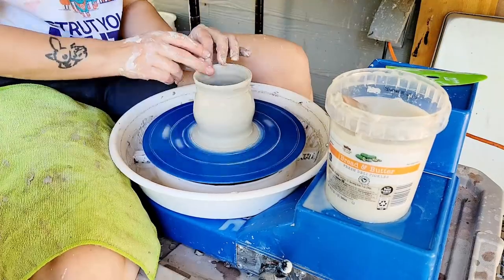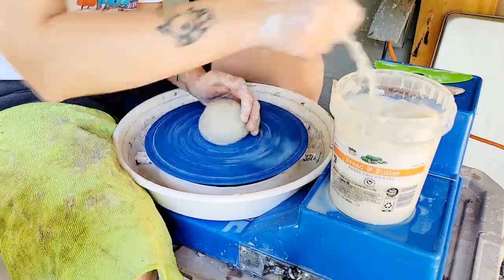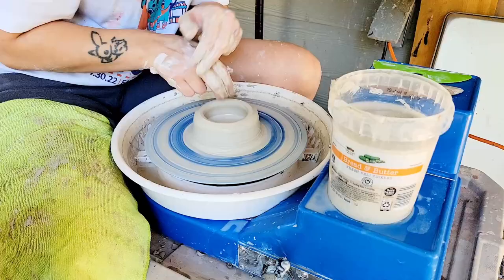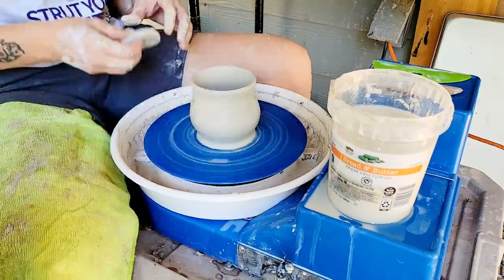The shrinkage for this clay is about 13% and the absorption when I tested it was under 0.1% at my hot cone 6. When I came across this clay, its beauty immediately blew me away and I had to find out how to get some. Industrial Minerals Company was able to ship me a 50 pound flat rate box to Texas.